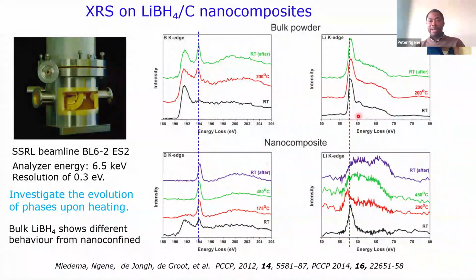Now, if you look also at the boron edge, we do see the same thing, that when you begin to heat, you begin to see these additional features that become more pronounced when you're heating the sample to a certain temperature. So here, if we come back to the nanocomposite, what do we see? When we compare the nanocomposite that we made, at room temperature, you already begin to see that this signature, which is here after heating, is already present at 194 eV. It's already present, even without doing anything. And immediately when we heat the sample just to 175 degrees centigrade, you see that it's completely this. So all the bulk-like behavior is gone. We only have this material.